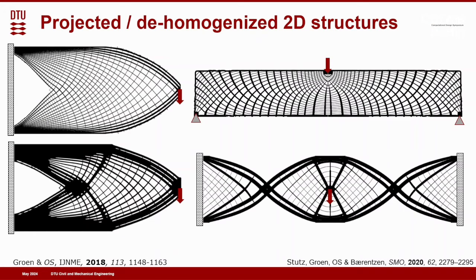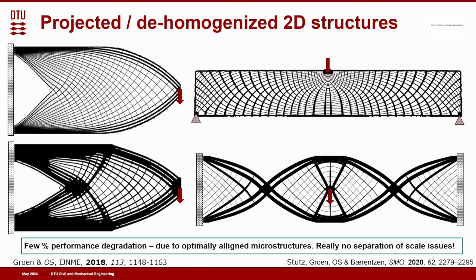These are some of the structures here, and you can sort of see that the form follows function here, right? This material is ideally oriented along the stress path all over. And interestingly also, we just have a few percent performance decrease compared to the theoretical optimum that comes from the homogenization-based solution. We get very close to these, but at a fraction of the time. Just to show you, this was a single load case. This here is multiple loading cases. That's also done by my other former PhD student, Peter, who is here in the audience.